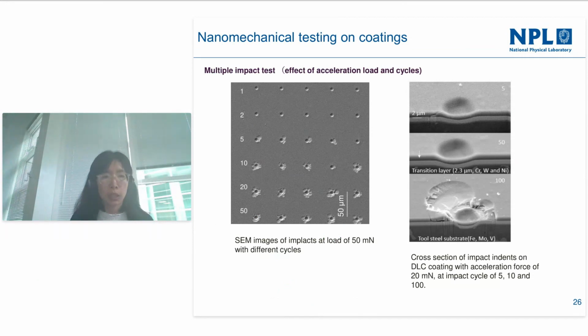By doing the multiple impact test, we found that we could map the coating's properties with the load and also the impact cycles. The left side shows images of impacts at loads of 50 millinewton with cycles from 1 to 50, and you can see the coating starts to peel, or fail, at about 5 cycles. On the right side is the lower acceleration load of 20 millinewton, and you can see the failure of the coating started at a much later stage.